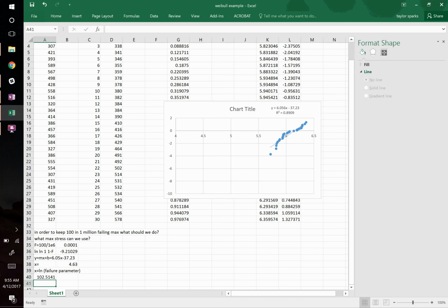Yeah, Barrett? Flaw distribution is going to be different throughout the larger material. And so you might have larger flaws that come out, say, in the center of it, depends on the material. So you don't want two different types of mechanisms. Otherwise, you can't apply Weibull analysis to it. You want it to be the exact same material, made the exact same way, just more of it. Because then, as Jared mentioned, the probability of having that flaw just gets larger and larger.